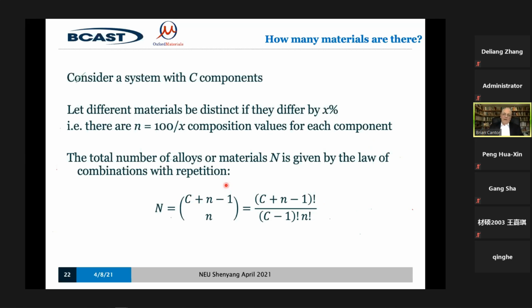So I hope I've explained to you that there are literally millions of new materials to be discovered because of this multi-component alloy concept. So let's look at it in a little bit more detail. How many materials actually are there? How many materials could we possibly make? Well, think about a system with C components. Imagine that we've got C starting materials and we can mix them up. And let's assume that we treat a material as different if it differs by X%. So if we change the composition of one of the components by 1% or 0.1% or 0.01%, we've moved to a different material. In other words, there are 100 over X composition values for each component.